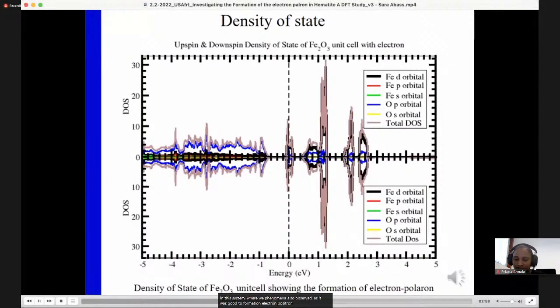We also look at the third case of having an electron in the system. We study the density of states and we show clearly the band gap. It also shows a state in the gap, and clearly shows the contribution to be oxygen with the p orbital in the valence band and iron with the d orbital in the conduction band.